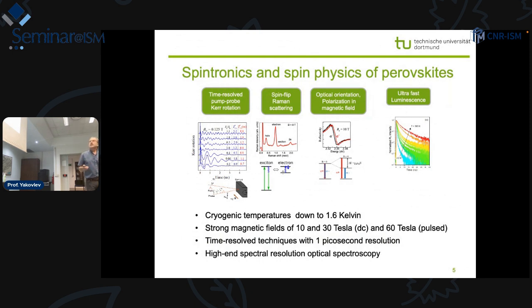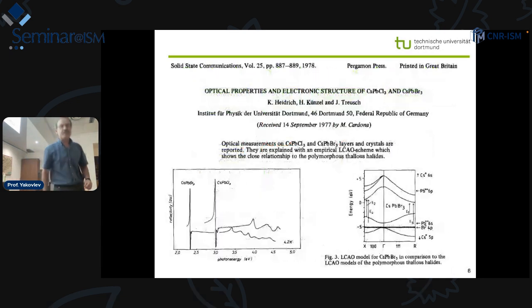What I wanted to present today is how these perovskites are good for spintronics and spin physics, and to present several experimental techniques: time-resolved pump-probe, Kerr rotation, spin-flip Raman scattering, and polarized optical orientation. I will talk about experiments mostly at low, cryogenic temperatures, but show some examples also up to room temperature. We use strong magnetic fields up to 10 Tesla or pulsed fields up to 30 Tesla, time resolution of 1 picosecond, and high-end spectroscopic resolution. So we sometimes need huge spectrometers for that.